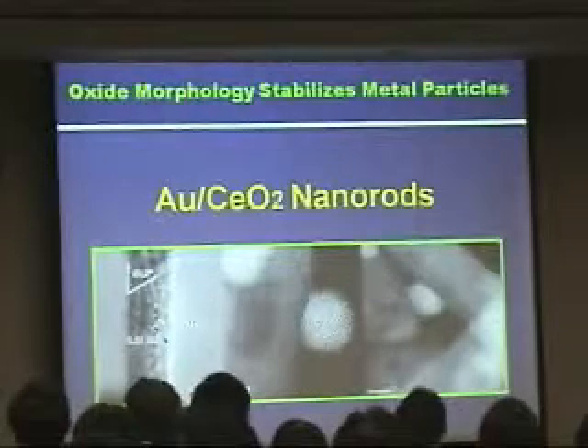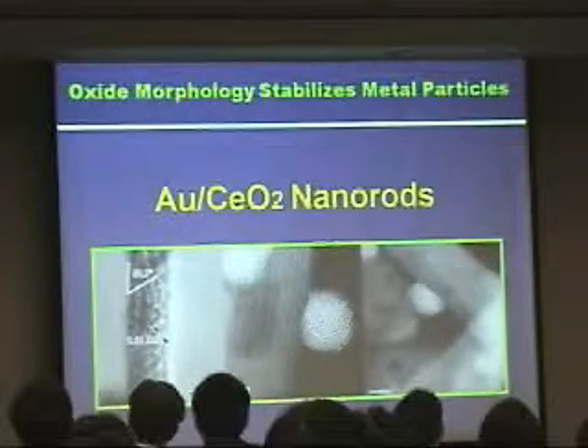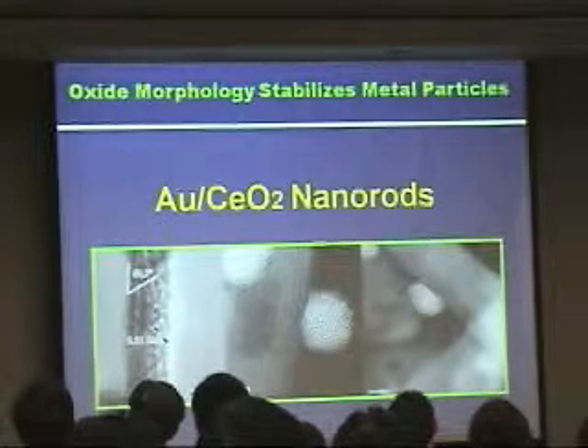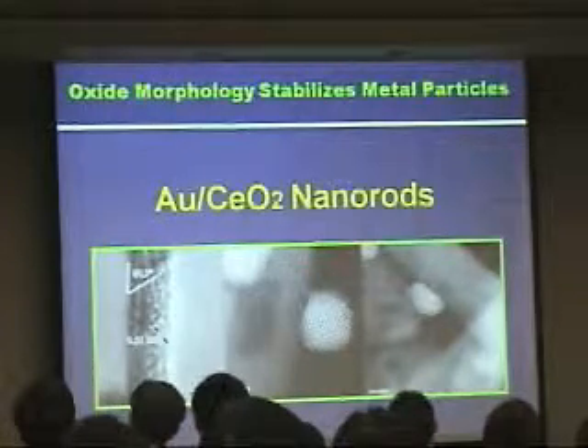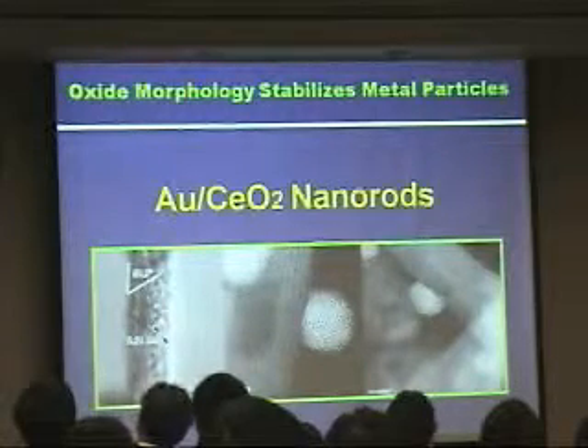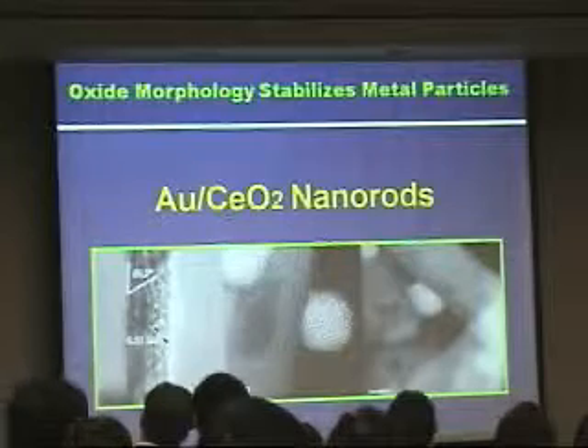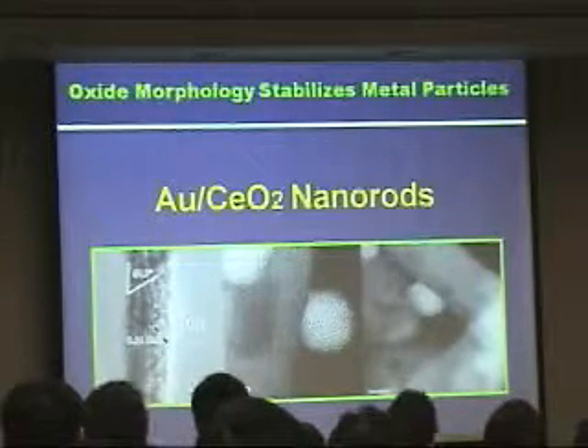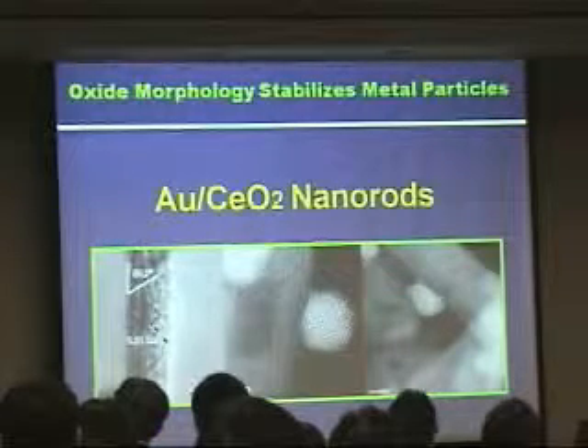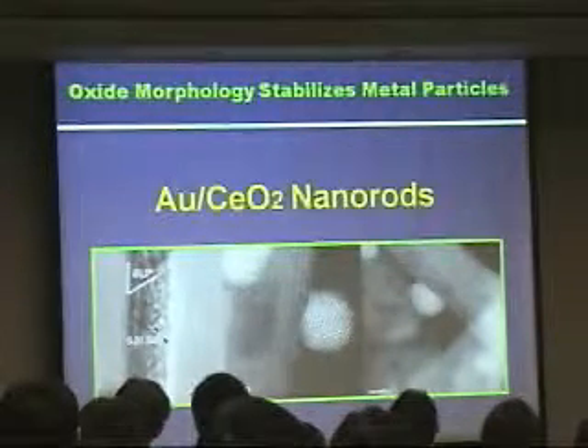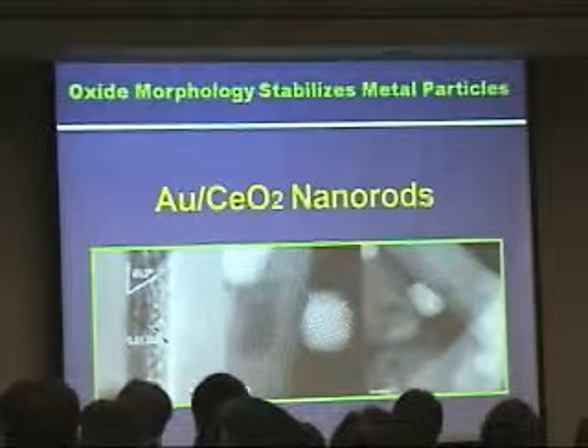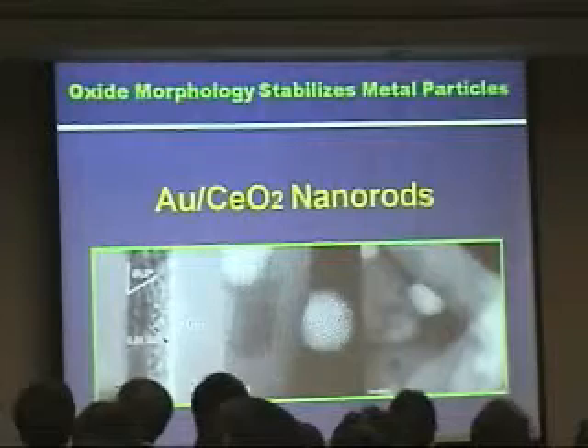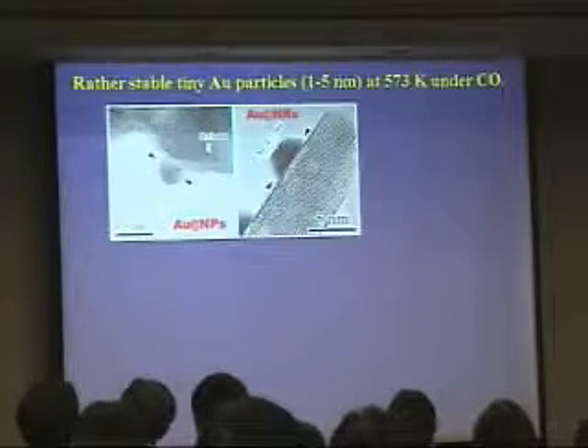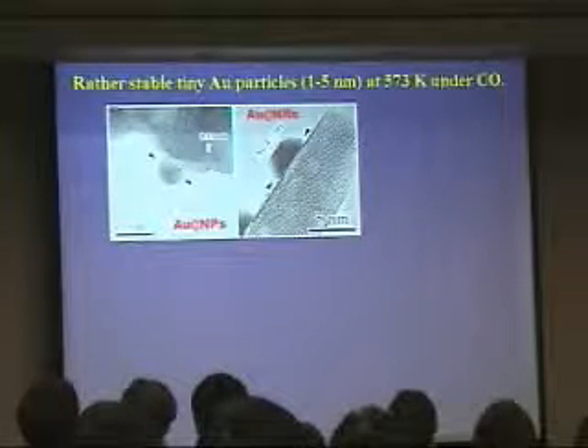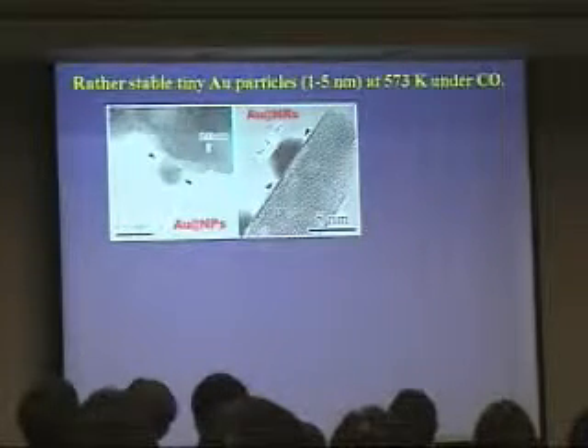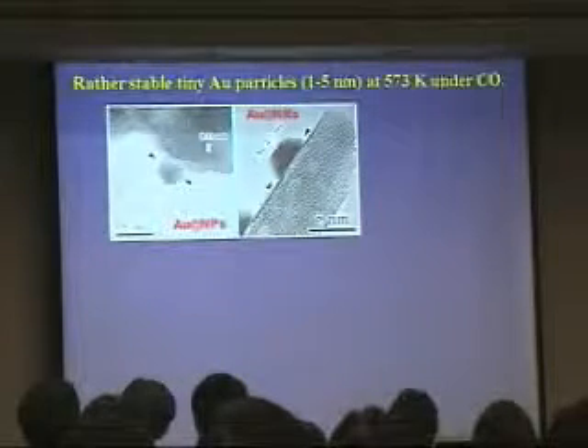And with these metal oxides, we want to see how they affect the interaction of coming metal particles. So this is a typical example using ceria nanorods to support gold nanoparticles. And we find this morphology of the support enhanced the stability of gold nanoparticles. Conventionally, ceria-supported gold is also very catalytic for a lot of reactions, because of high activity for water gas shift and CO oxidation.